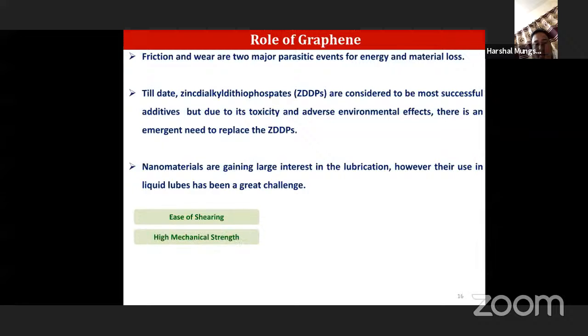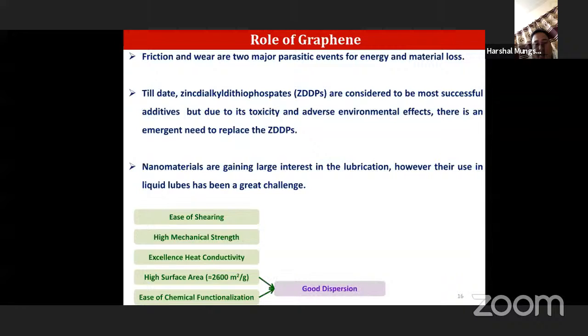This material has very good tribological properties because it is easy to shear, it has high mechanical strength, as we have already seen, excellent heat conductivity, high surface area of nearly 2600 square meters per gram, and ease of chemical functionalization. Now how do these factors affect? Because of the high surface area and ease of chemical functionalization, we can easily functionalize this material, and because of this functionalization, it can easily disperse in the lube base oil. Then the ease of shearing, high mechanical strength and excellent heat conductivity help to reduce the friction and wear.